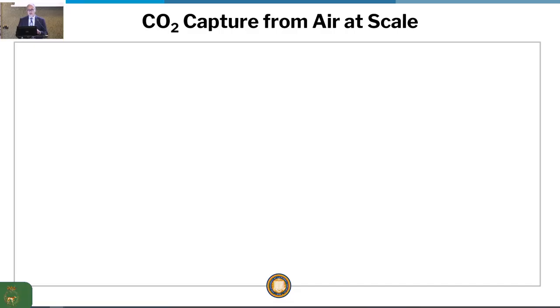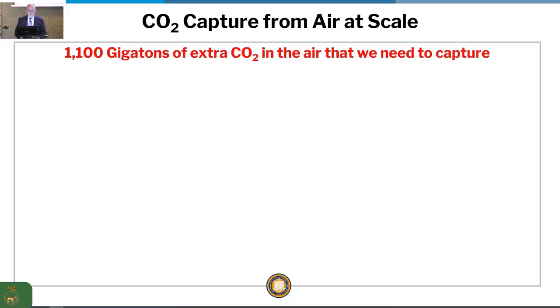So I like to say that the CO2 capture problem, the scientific problem, is solved. Yeah. This challenge is solved. This material can cycle and cycle for 6-7 years. Why? Because the chemistry of the backbone allows the backbone to be robust. So now we want to talk about what you need to make this scalable or to operate this at scale. In the air today, there's 1,100 gigatons of extra CO2 that we need to capture. This is the additional CO2 we put into the air as a result of burning fossil fuels.